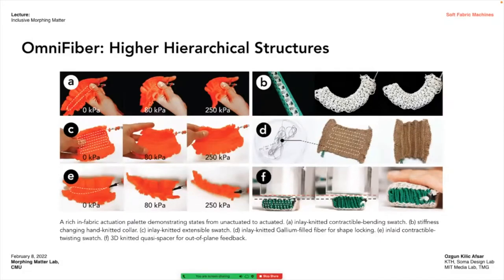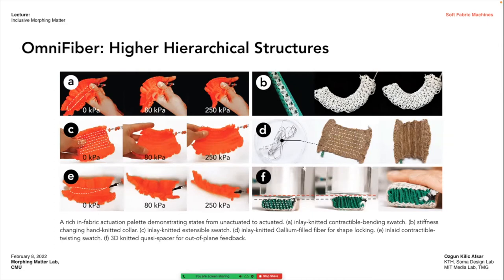Scaling fibers to higher hierarchical structures like woven fabrics also increases force output. Assistive technology requires considerably high forces — tens or hundreds of newtons — to move a spine or limb. This can be achieved through weaving or braiding the fibers to improve mechanical performance and force output. One can also operate the fibers in hydraulic mode, filling the tubing with liquids driven by pneumatics. Due to the incompressibility of liquids, larger stresses occur on the fiber body, providing larger and more precisely controllable contraction forces.